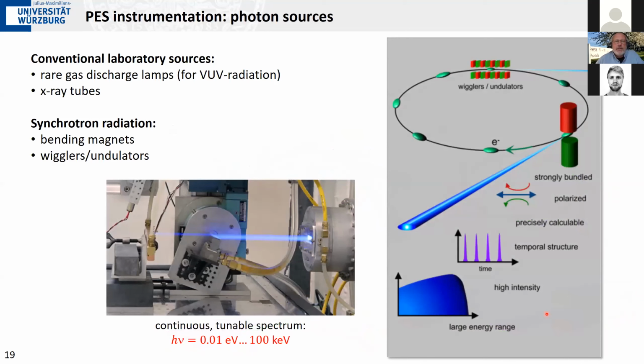Now, why would we do this? What is the big advantage of this radiation? Well, first of all, you have a very wide, continuous, tunable energy range. You can, in such a storage ring, induce photons from the infrared to the very hard X-ray regime, from 0.01 electron volts, from millivolts, that's infrared, to gamma rays of the order of 100 kilo electron volts. So this is a huge range, and by suitable monochromators, you pick out the photon energy range that you want to use.